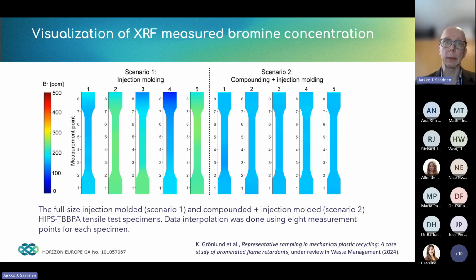So the same story, but now doing in a more quantified manner, which we have seen in the visual study, is that indeed there is a significant variation of the bromine content if we just do the injection molding, simply depending on which are the flakes that happen to be on the stream as we are forming the dog bones. Whereas then once we do the compounding in between, we see that there is a much more even distribution of the brominated species along the dog bones as one would expect. And for these ones, the data interpolation was done using 8 measurement points for each of the specimens.